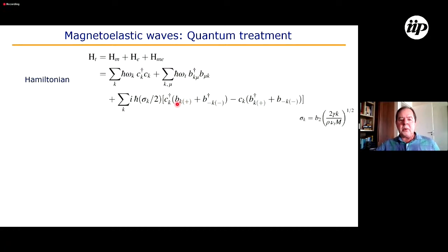Notice that this operator, b_k plus, is an operator for a circularly polarized phonon. Circularly polarized phonon in the plus direction, and this is the minus direction. So this term here, for instance, represents destruction of one magnon and creation of a circularly polarized phonon with the plus sense.